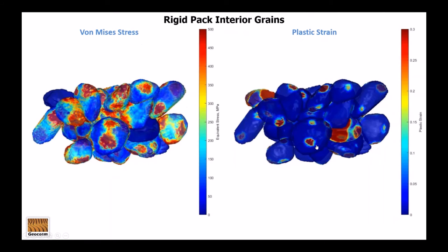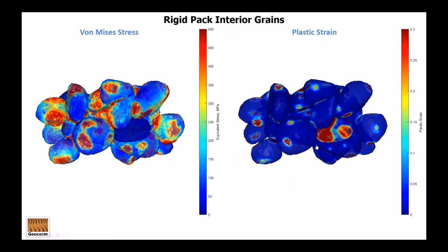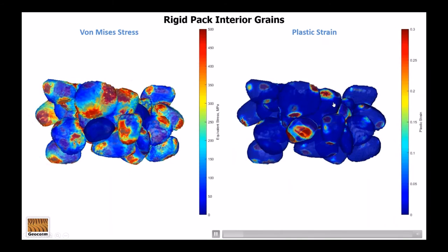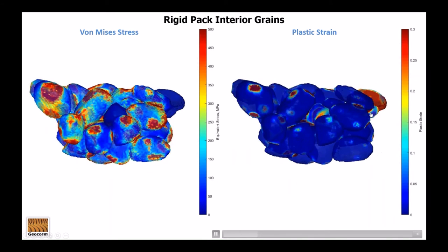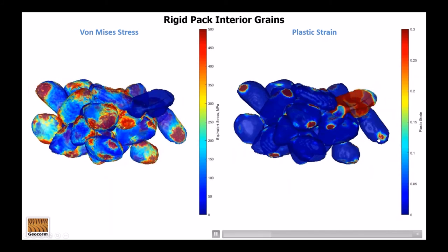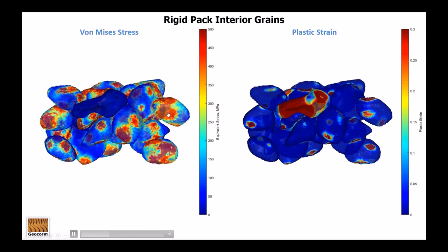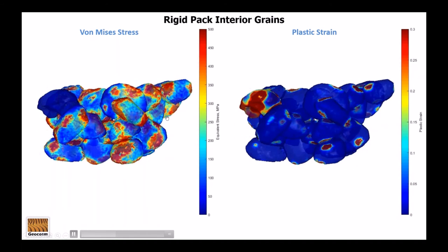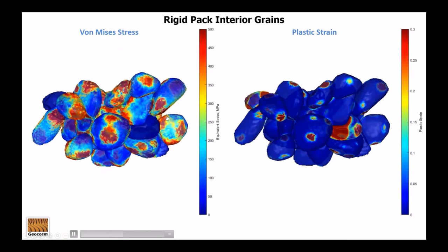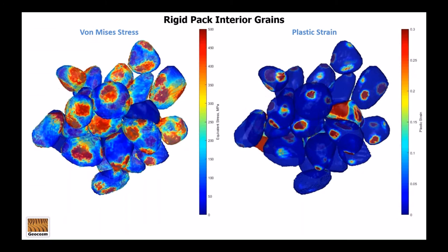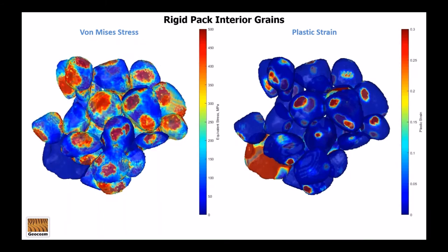Just looking at that rigid grain rich pack, we have the stress on the surfaces of the grains on the left and the plastic strain on the right. These dark red symbols show very nicely where the contacts are between these grains. And we can also see over here what the stresses look like on those grains, which, as I mentioned, will be very important for trying to get at rock physics behavior in sandstones.